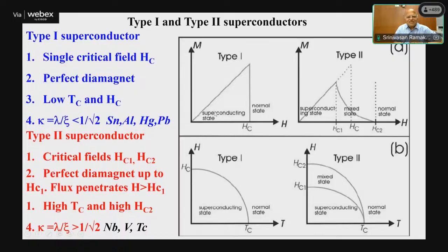How does the magnetization behave? So the magnetization for a type 1 superconductor is like this. You have a superconducting state, then it goes to the normal state at the critical field. In the type 2 case, it behaves like a Meissner state only up to Hc1, then the flux penetrates. It's called the mixed state. And at Hc2, it goes to a normal state. So there's only one critical field for type 1. There are two critical fields for type 2. One is Hc1, up to which you see a perfect Meissner effect, and then Hc2, above which it is normal, with a mixed state in between.